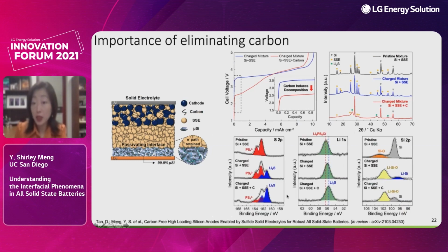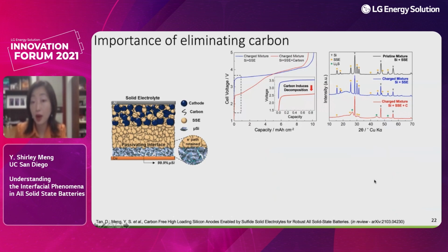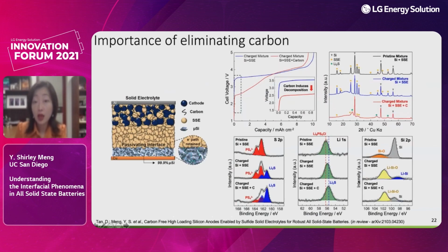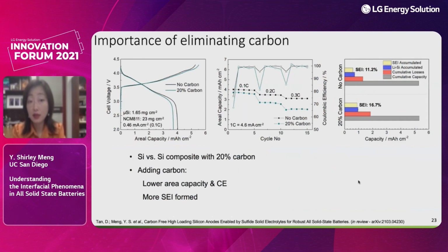The XPS also clearly shows the same observations, because sometimes the decomposition product is not very crystalline, and we can use X-ray photoelectron spectroscopy to detect those decomposition species. So in the cell performances, you can easily see that eliminating carbon gives you better utilization of the silicon anode, and the interface can be stabilized very quickly after the first cycle.